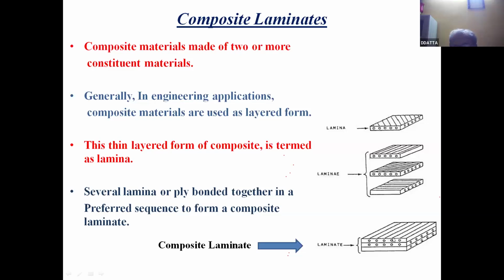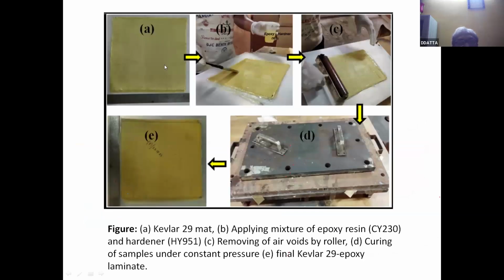So in this last part, composite laminate, here is a drawing. There is a 3-ply laminate which can be used for some structural applications. This is a typical diagram of one of my students making a composite laminate. Here you can see a ply being laid one over the other, and in between, the epoxy resin mixture is being applied on the surface by a brush. This is a hand layup technique.